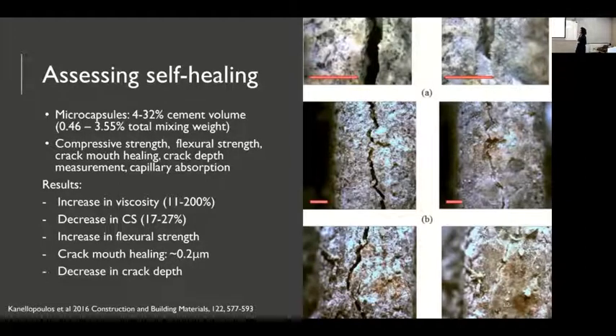When we were assessing the self-healing capacity of these microcapsules, those are the concentrations that were investigated. And what we see is that, yes, there is an increase of viscosity and a decrease in compressive strength by adding these microcapsules. And that's an interesting point. When we were talking about the crack mouth healing, it was around 0.2 microns. But a decrease in the crack depth was also noticed by adding these capsules for self-healing.